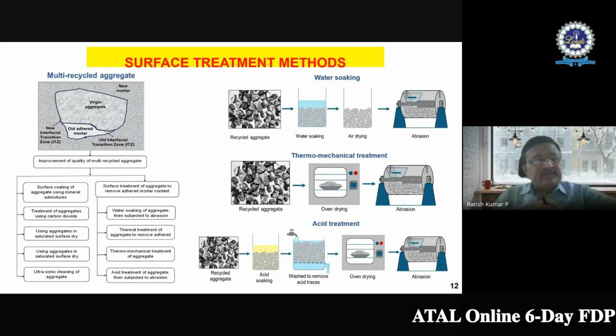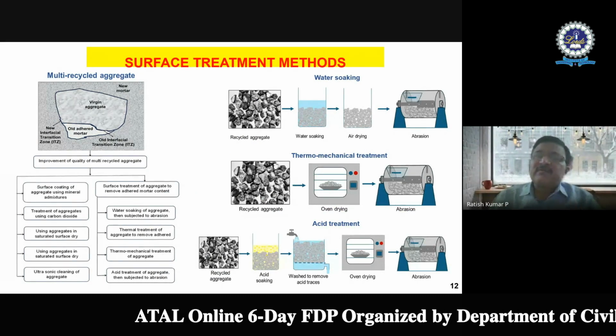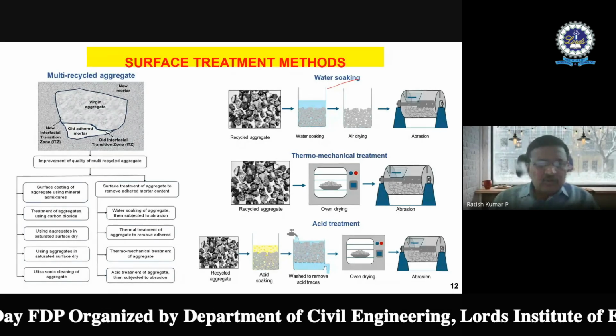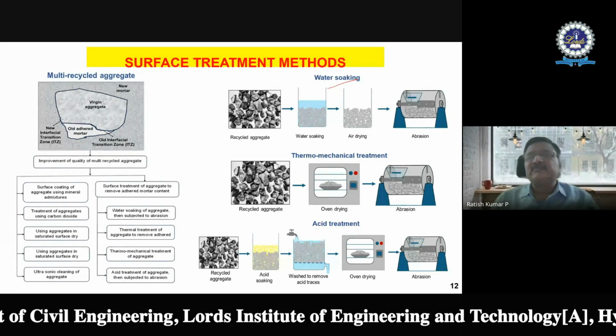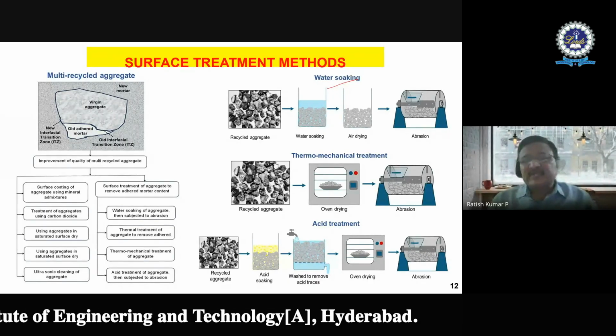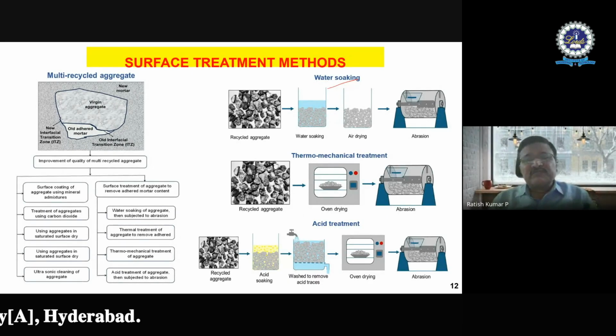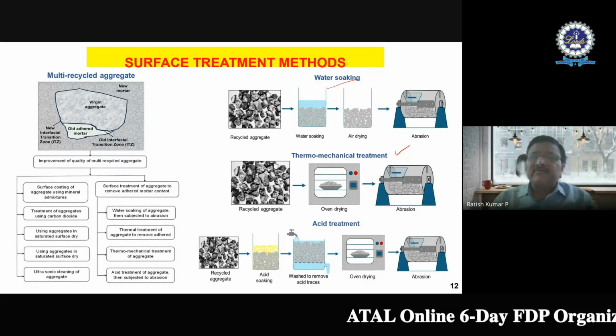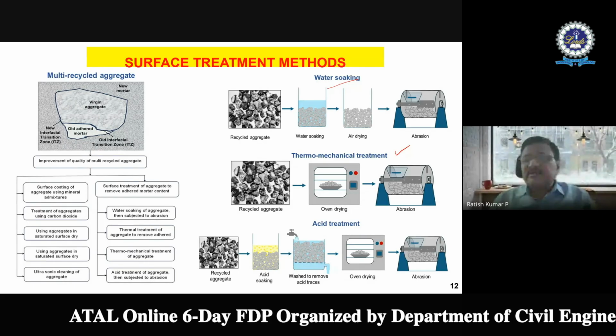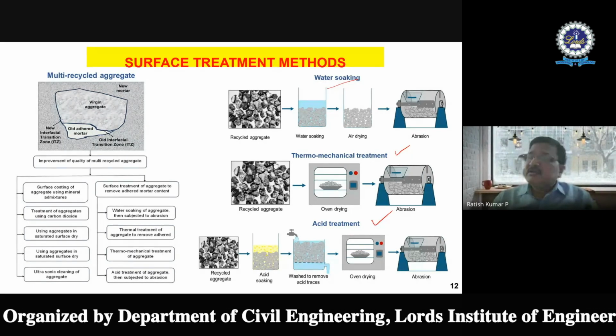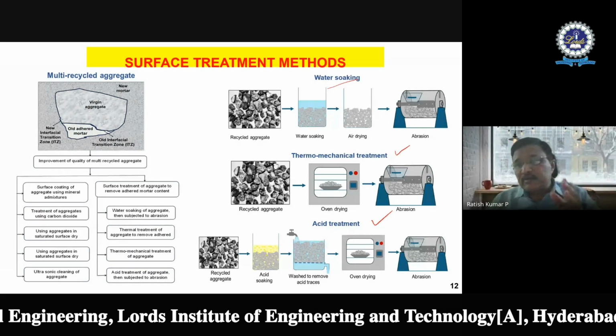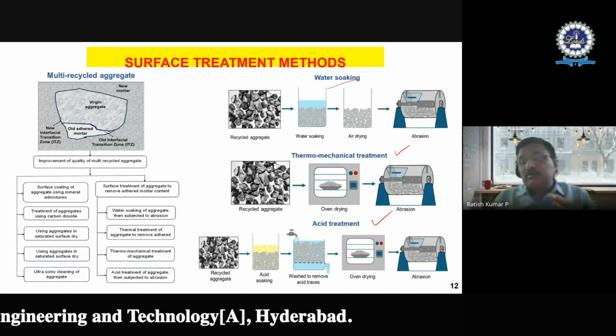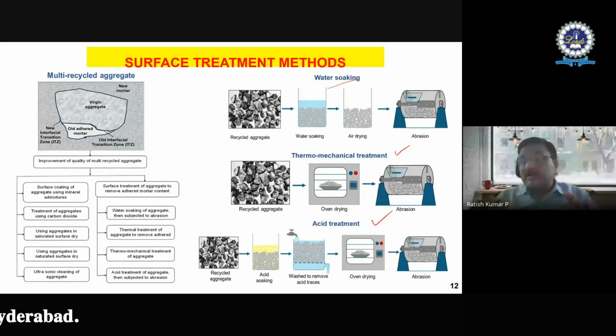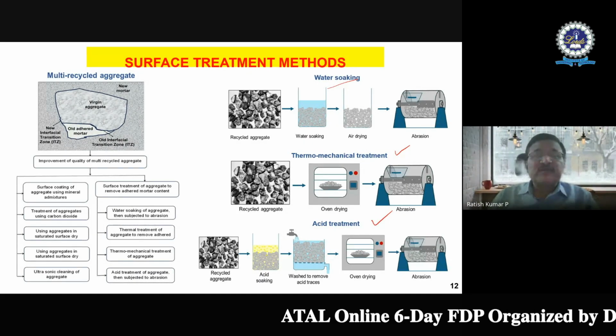Now, these are some of the surface treatment methods. As you can notice, one of the methods is water soaking, which to some extent can be effective. Then we can go for abrasion and get a certain amount of removal of the old mortar which is there. I think it's better if you go for a thermomechanical treatment type of method, where you do the oven drying and then go for abrasion. And then there's another method which is still better, called acid treatment. But when you go for acid treatment, what am I also doing to the aggregate, how much treatment has to be done, and how much damage I'm doing to the aggregate is also one thing which I have to talk about.